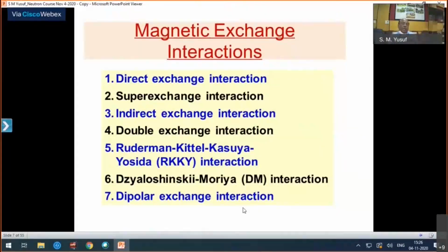One can do this calculation. You can go back to your Kittel book, and you can see that the interaction will be very small. So how do you translate? If J is very small, that means if you had to get magnetic ordering out of only the classical dipole-dipole interaction, then magnetic ordering could not typically be above 1 Kelvin.